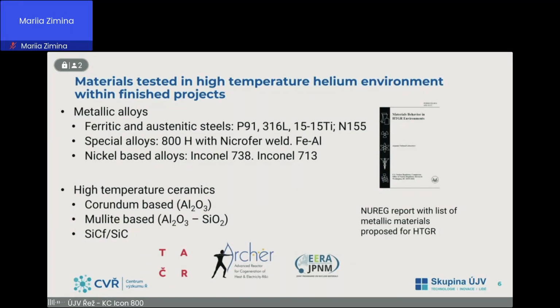Since there are many components, from the pressure vessel, either HTR or GFR, which can probably be from ferritic, but most probably austenitic steel for GFR. Then we have the secondary circuit that must be from nickel-based alloy. At this moment, there is the code 800H, but also 617 nickel-based alloy. Then for several phases, the candidate material for cladding is 15-15 titanium, what Lukáš already presented for the LFR condition. And for the higher temperature, for phase 2 of Allegro, where 850 is expected, we are researching the ceramic materials.